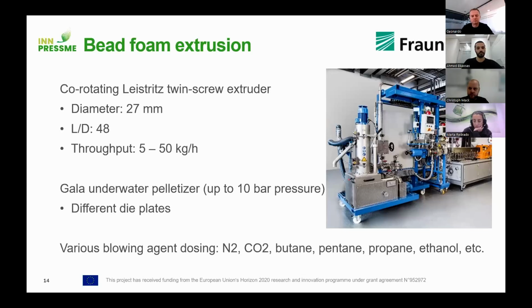For the bead foam extrusion, we have a Leistritz twin screw extruder with a 27 millimeter screw and a throughput of up to 50 kilograms per hour, a Gala underwater pelletizer with up to 10 bars pressure, and we can dose various blowing agents, being CO2, nitrogen, pentane, propane, ethanol, so more or less all that are common in the foam industry.